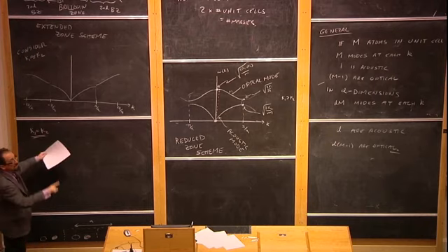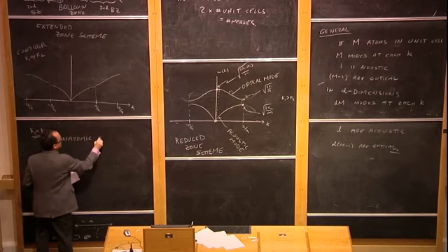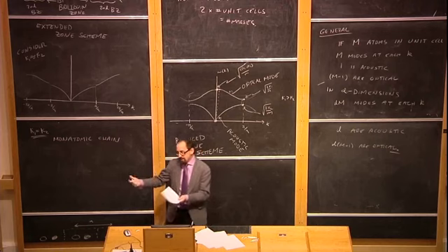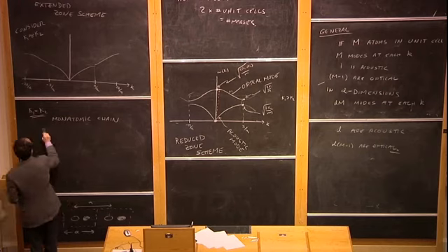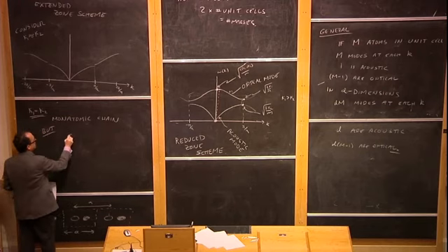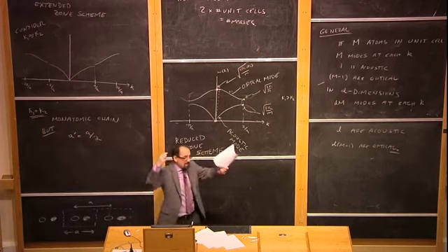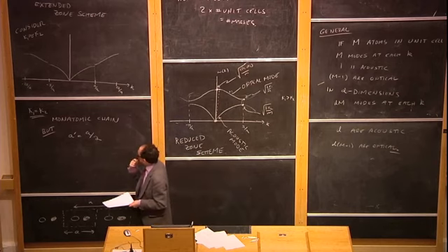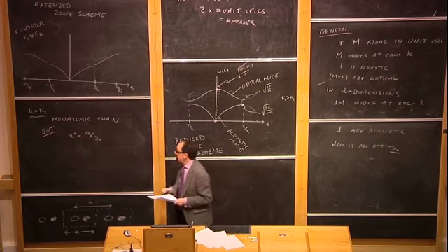Well, then what we have is the gap closes. It becomes a single connected line. But more importantly, we recover the monatomic chain. Right? If kappa 1 equals kappa 2, then every mass and every spring is the same as every other mass and spring. So we get back the monatomic chain. But the lattice constant has changed. The new lattice constant is only half as big as the old lattice constant, because the white and black masses now actually are the same. They're the same object now, so we don't have to make a unit cell with 2 things. We now make a unit cell with only 1 thing in it, right?